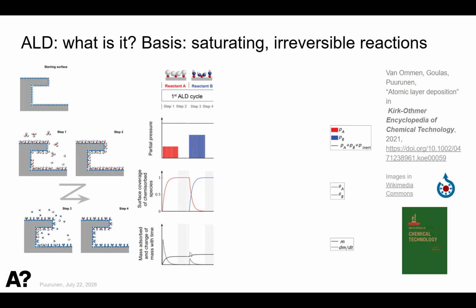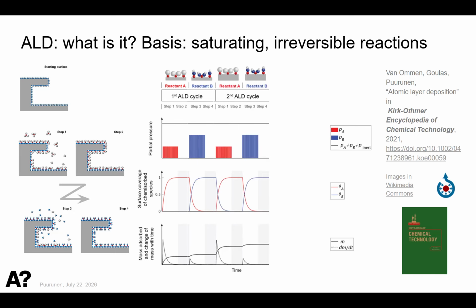Sometimes actually the change can also be negative. So depending on what the masses of the ligands that get removed are and what is coming on the surface, this can also go down. But when you look at the full cycle or sequence of steps, of course, in total the mass should go up, and if it's not, then it would be atomic layer etching, which is a closely related technique.